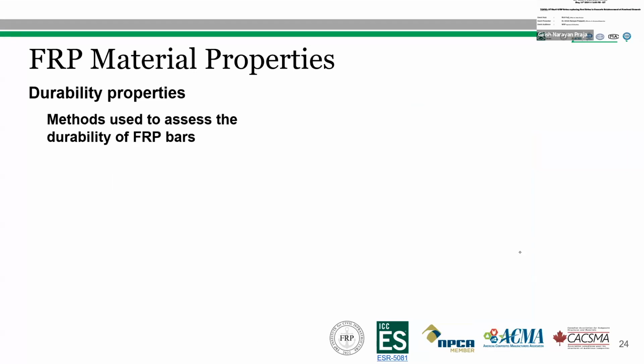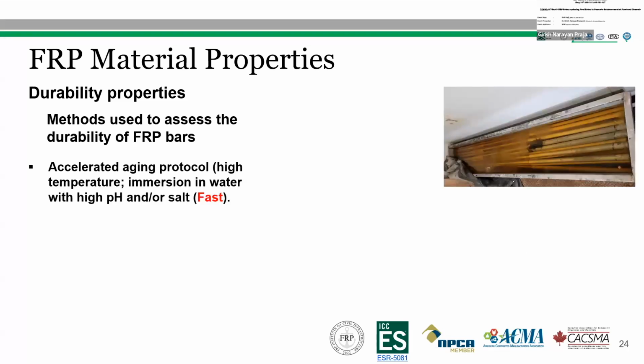The methods used to assess and validate the durability of FRP bars are accelerated aging or alkaline tests. In this case, we immerse the FRP bar in water with alkaline salt under high temperature. The temperature is usually 60 degrees Celsius. This is a fast process, and the test is conducted after 3 months of immersion or exposure to the alkaline salt.